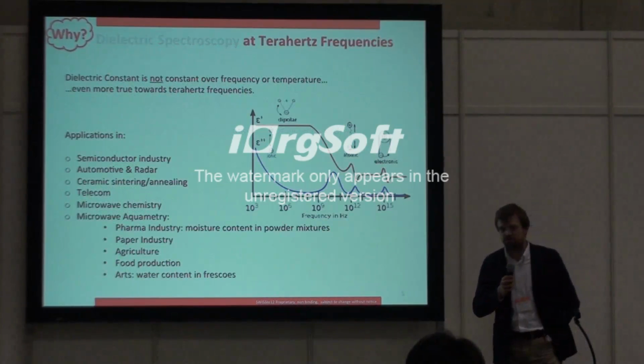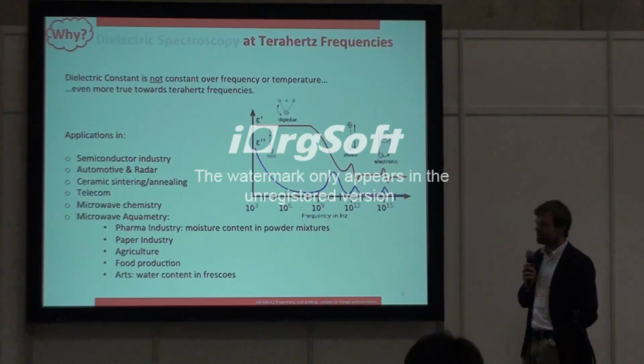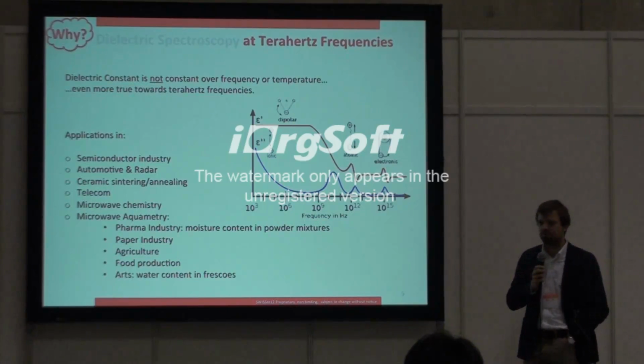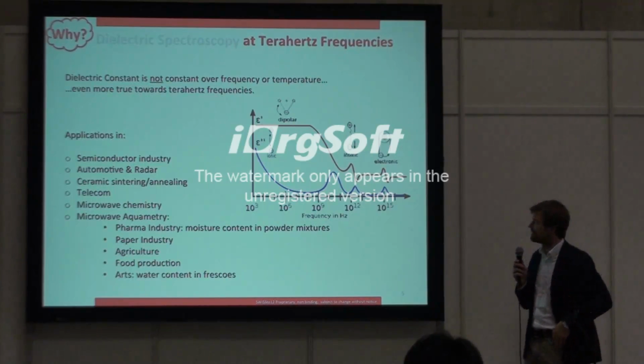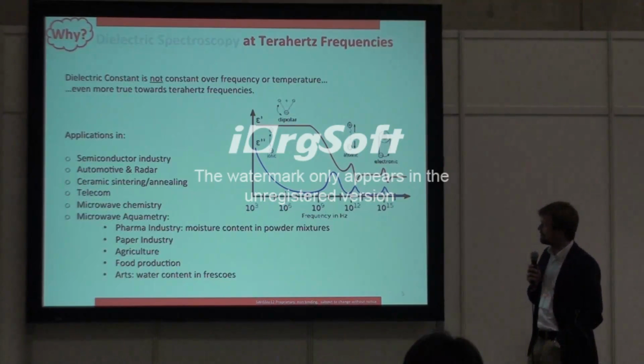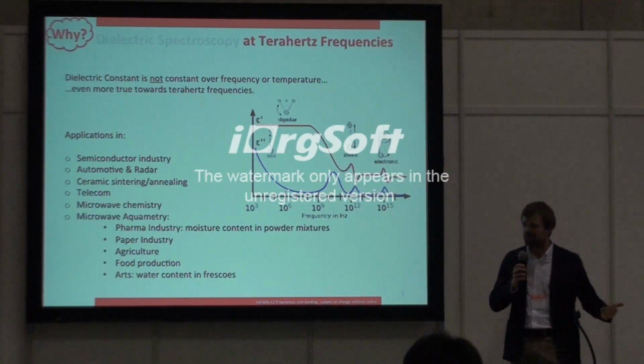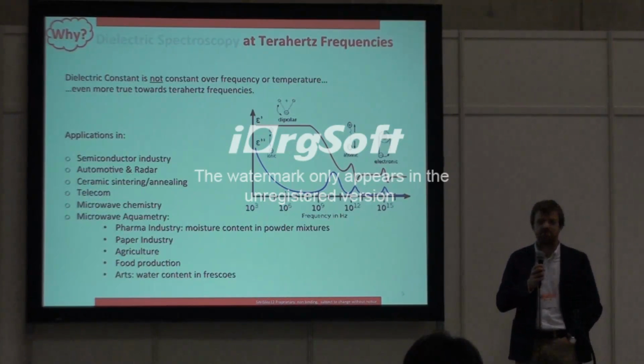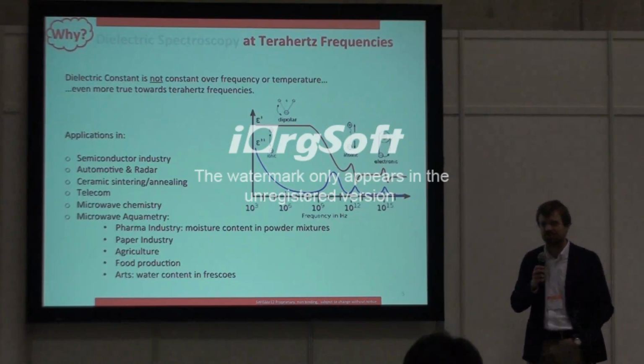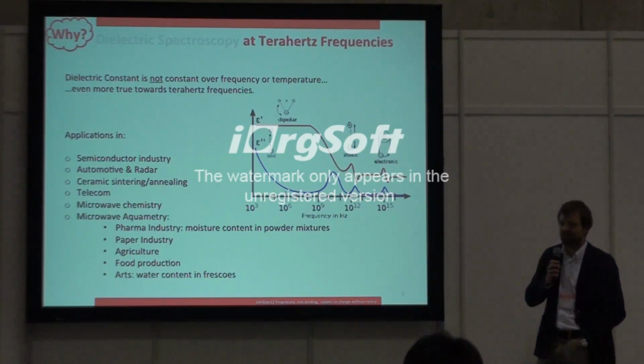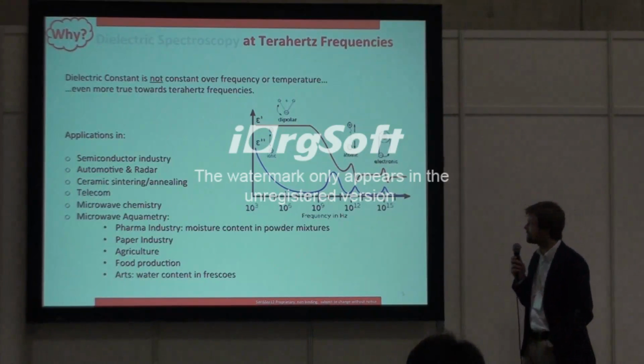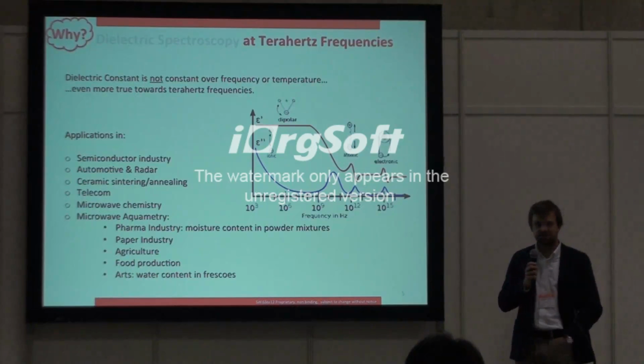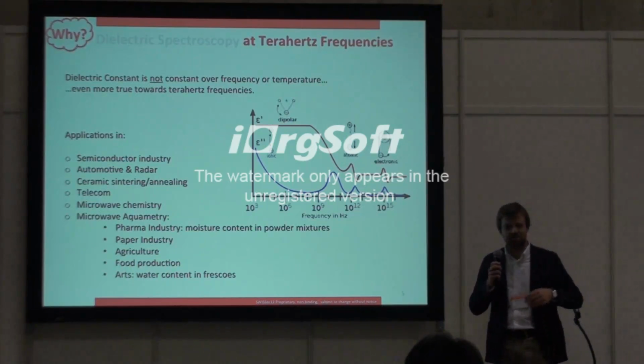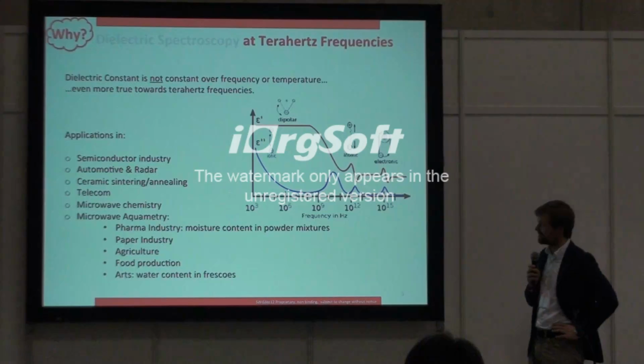So when you do permittivity measurements with dielectric spectroscopy on materials, depending on the wavelength at which you operate, you are interacting with different mechanisms in the cell. And for the people coming from lower frequencies, some microwaves, and moving up, we often have permittivity values that vary very little over frequency, so that the dielectric constant is actually constant over frequency. But when we reach the millimeter wave and terahertz range, we start to enter into a regime where we see some atomic effects, and where this dielectric constant is no longer constant, and thus where spectroscopy becomes interesting.